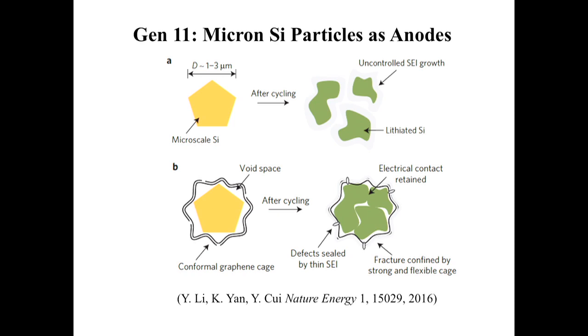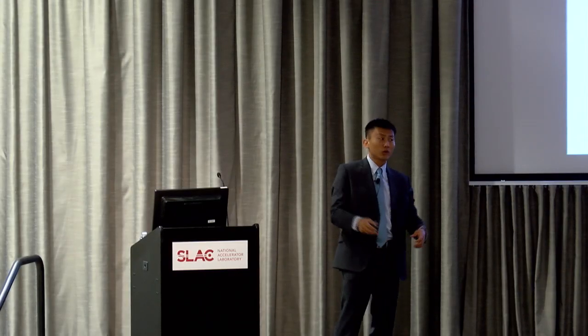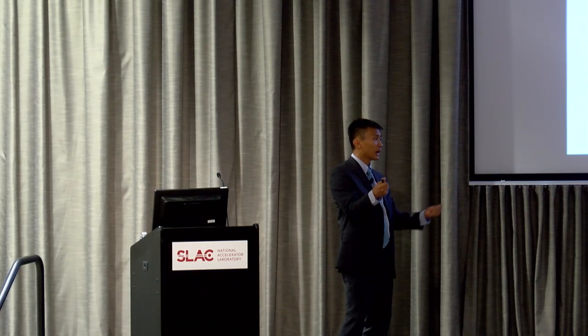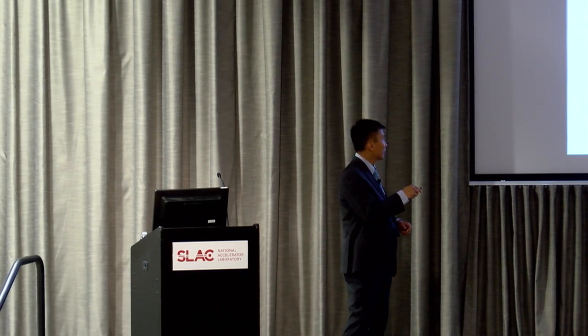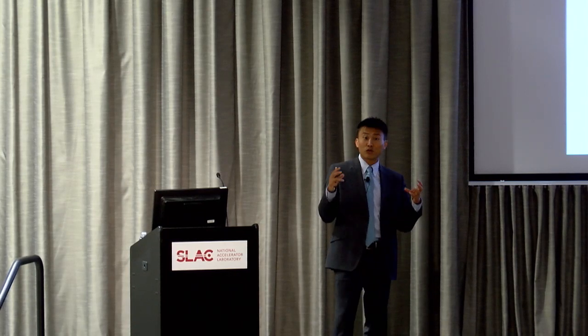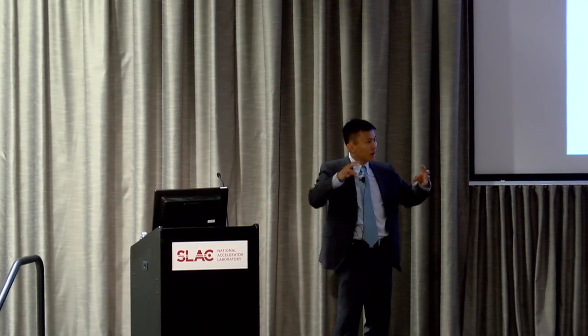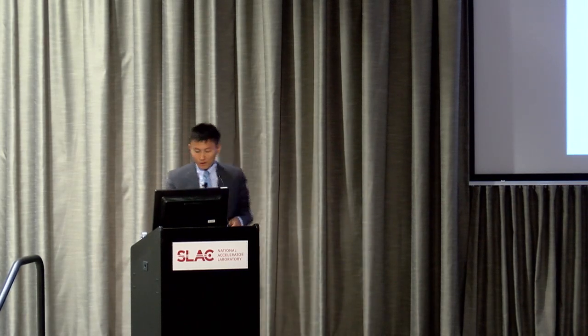Let's find the strongest cage right there. So it turned out, in the past 15 years, you heard about the Nobel Prize for graphene. Graphene is very strong mechanically. It's conducting electricity. So if you can build multi-layer graphene, that's basically graphite, right? And when volume expansion happens, you leave some empty space right there. If you don't leave that, even graphene cannot hold it because volume expansion is 4 times. It will break your chemical bonding of carbon-carbon. Leave some space. And this graphene, we expect they're strong enough to hold their shape, to try to keep all the silicon inside. So we made this.